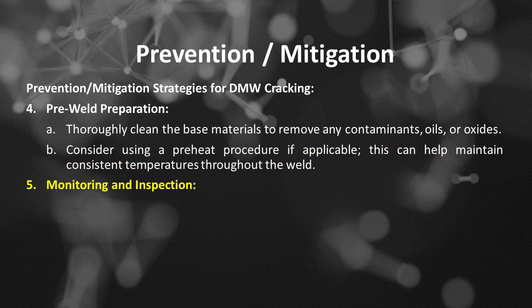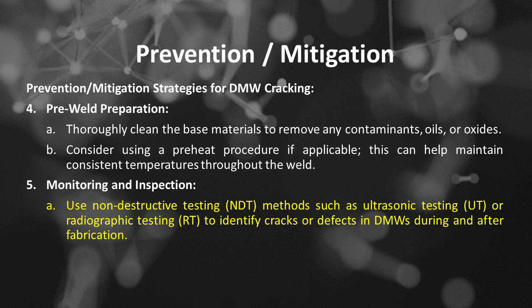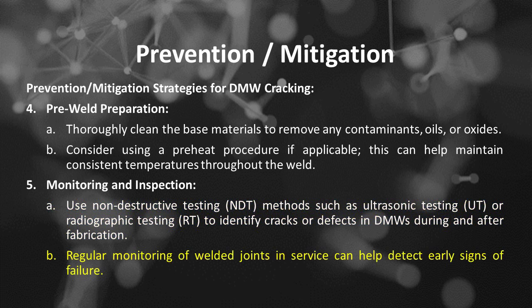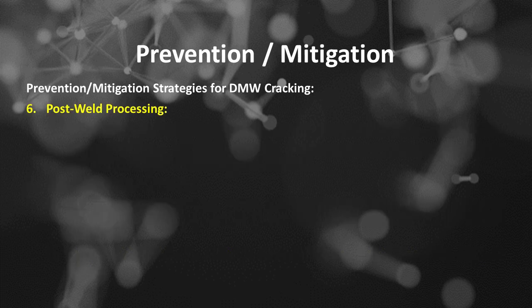Include: the first is use non-destructive testing, or NDT, methods such as ultrasonic testing, or UT, or radiographic testing, or RT, to identify cracks or defects in dissimilar metal welds during and after fabrication. The second is regular monitoring of welded joints in service can help detect early signs of failure. Number 6 is post-weld processing.